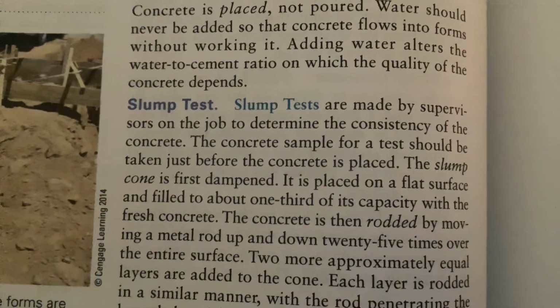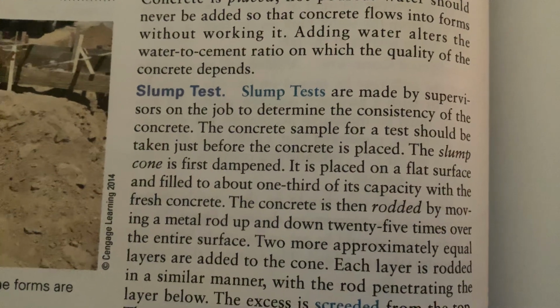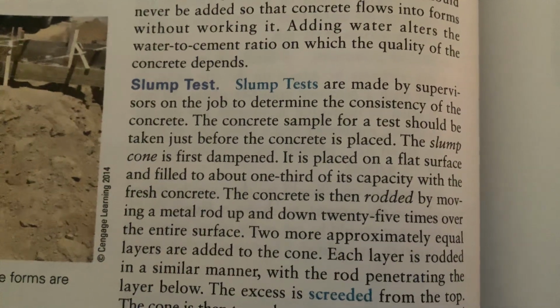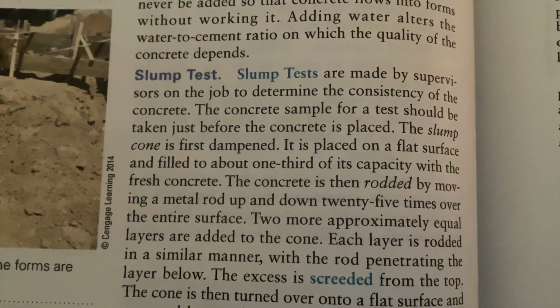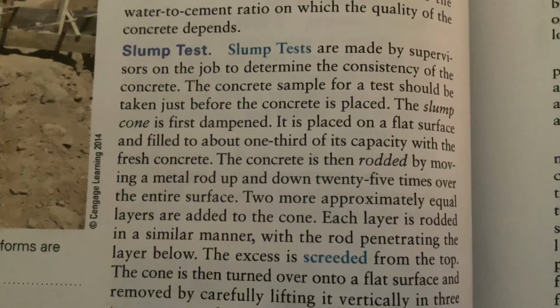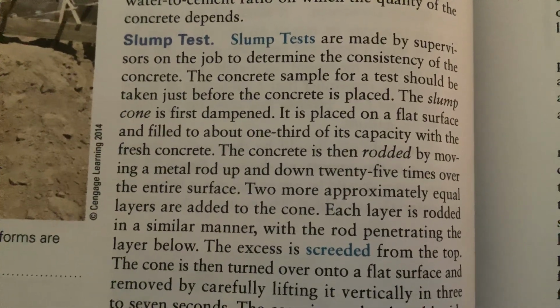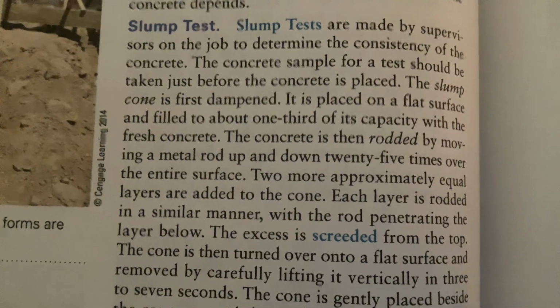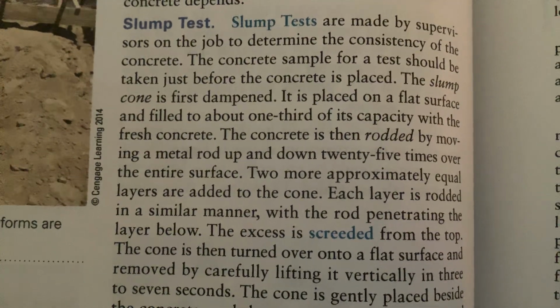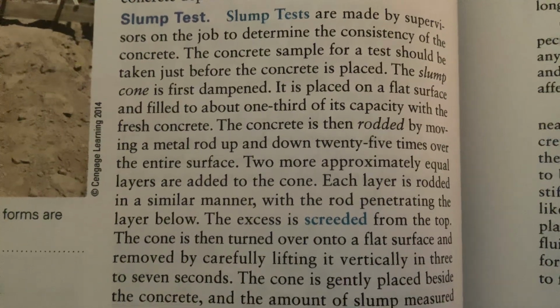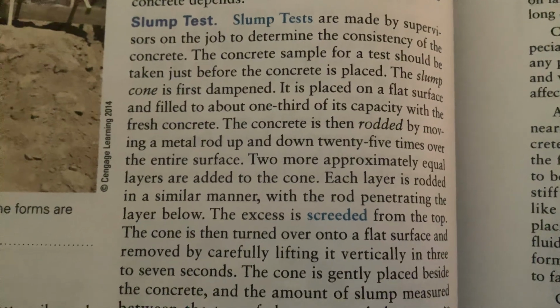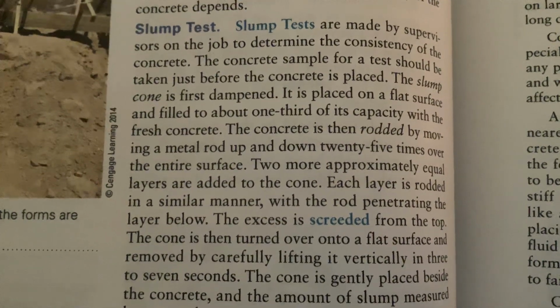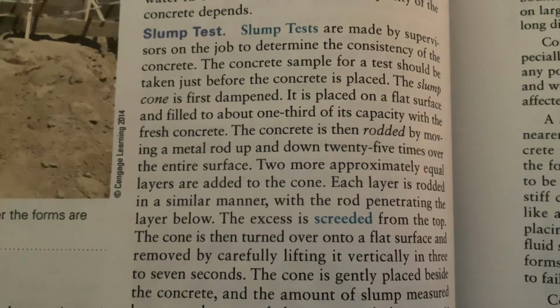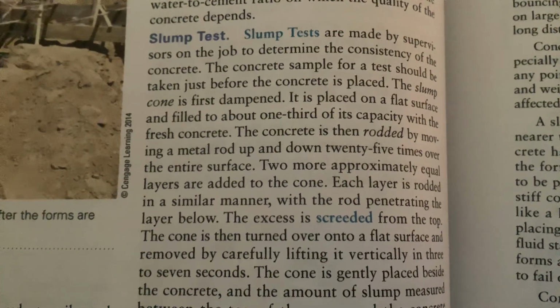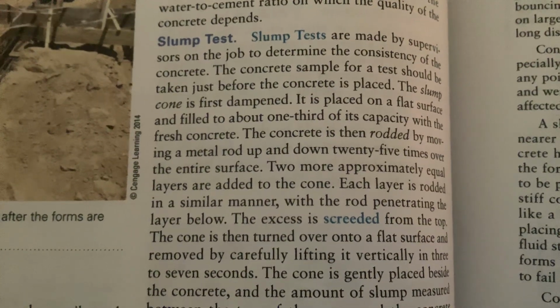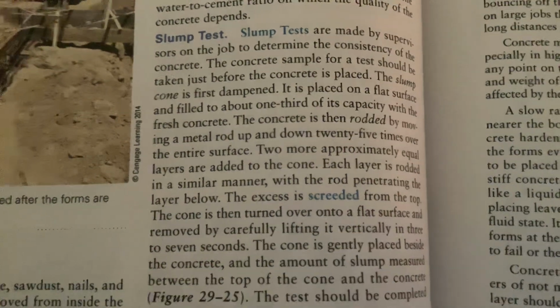Slump tests. Slump tests are made by supervisors on the job to determine the consistency of the concrete. The concrete sample for a test should be taken just before the concrete is placed. The slump cone is first dampened, placed on a flat surface, and filled to about one third of its capacity with fresh concrete. The concrete is then rodded by moving a metal rod up and down 25 times over the entire surface. Two more approximately equal layers are added to the cone. Each layer is rodded in a similar manner, so that the rodding penetrates the layer below.